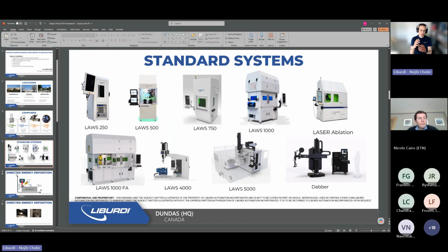Once you have the machine built, we commission it and use laser technologies that provide what we call compensation tables. The gantries that you purchase usually have an inherent deviation by essence. We measure that deviation using highly precise lasers that give feedback like linearity, the squareness between each axis, and the dimensional precision. So when you move 1 inch, it's actually 1 inch to the micron. Sorry, I'm used to imperial here, but if you say 20 millimeter, you'll be at 20 millimeter to